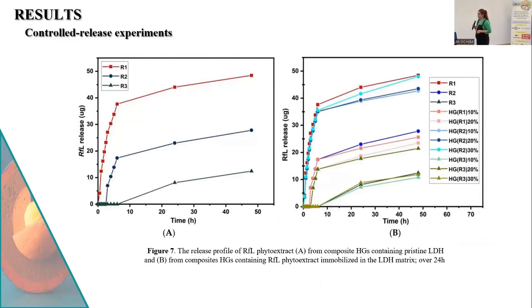Also, in the controlled release experiments, we can observe that the phytoextract is released slower in time in the case of the phytoextract inside the LDH. And we also have a slower release in the case of the hydrogel with the LDH and the phytoextract. This can be attributed to the fact that there are some interactions between the LDH and the PEGDA chain and the Ramulus frangula molecules.